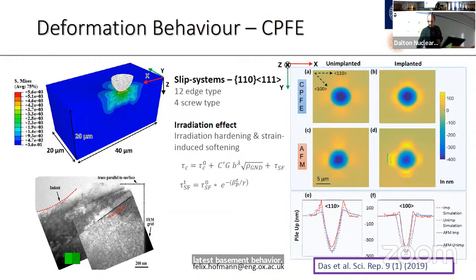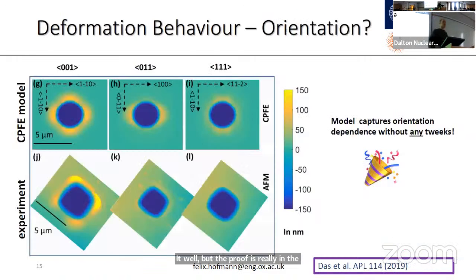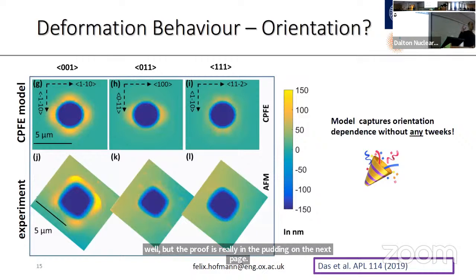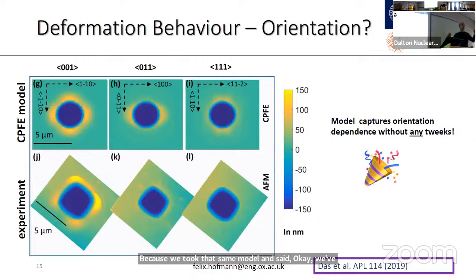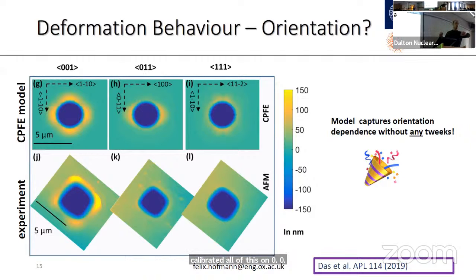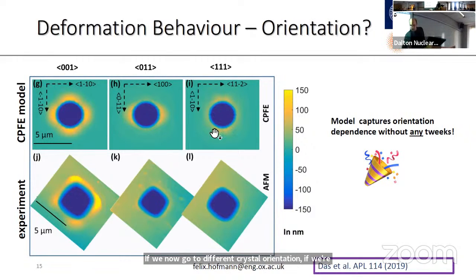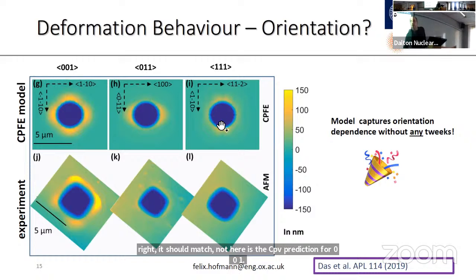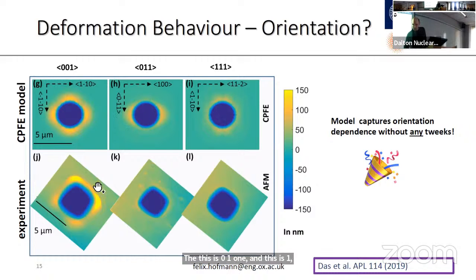But the proof is really in the pudding on the next page, because we took that same model and said, okay, we've calibrated all of this on a 001 oriented crystal, right? If we now go to a different crystal orientation, if we're right, it should match. So up here is the CPFE prediction for 001. This is 011, and this is a 111 oriented crystal.